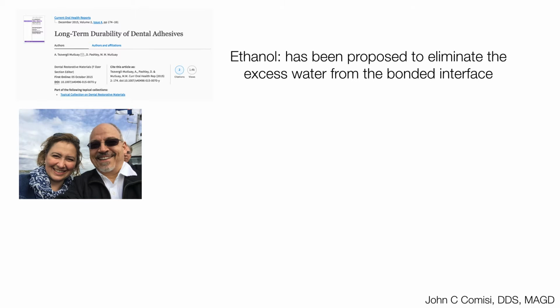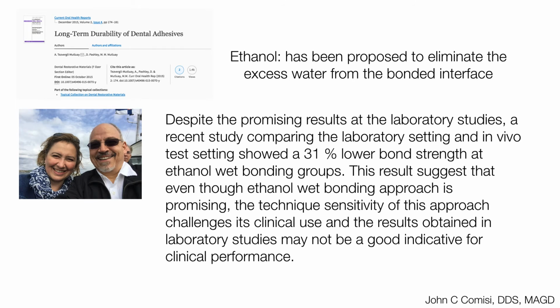Ethanol has been proposed to eliminate excess water from the bonded interface. But as is stated in the article, despite the promising results at laboratory studies, a recent study comparing laboratory setting and in vivo testing has showed a 31% lower bond strength at the ethanol wet bonding groups, suggesting that even though the ethanol wet bonding approach is promising, the technique sensitivity of this approach challenges its use in clinic, and results obtained in laboratory studies may not be a good indicator of clinical performance.